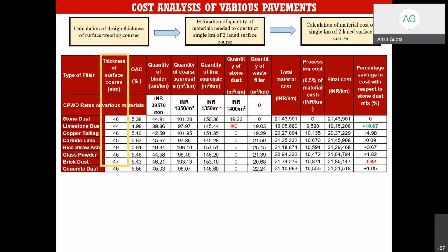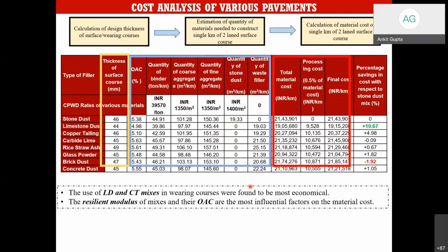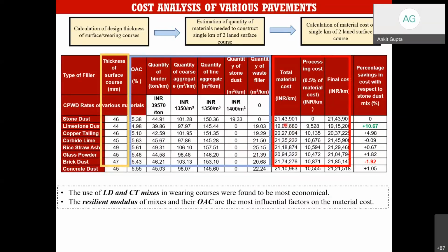Here, obviously, because we are using all these wastes, these are free of cost. Okay. And one good thing that we have done in this experiment is we have taken the waste directly from the source without any treatment. There is no treatment except the sieving, which we have done for the 75 micron. Okay, and this is the quantity of the waste filler which we have used. So now we can find out the total material cost. This is an approximate cost for the processing of the material, although we have not done any kind of processing except the sieving of these wastes. But still we have added 0.5% of the material cost for the processing of these wastes.